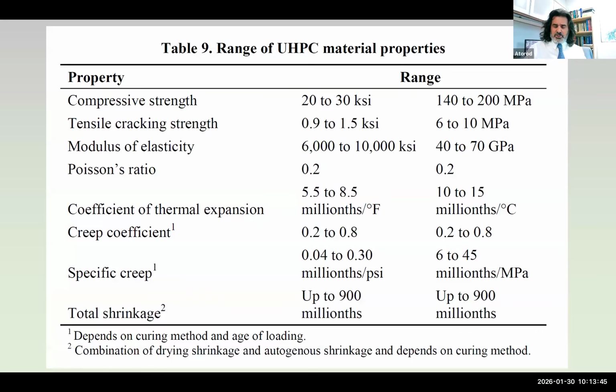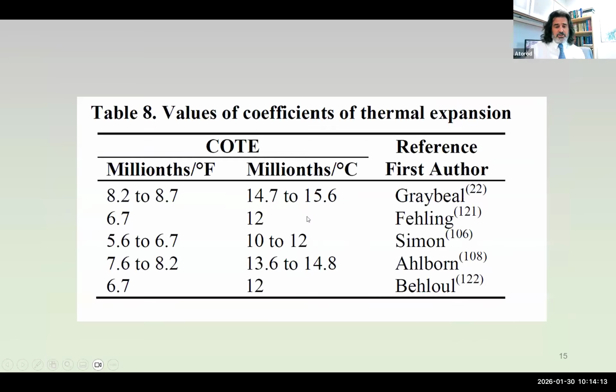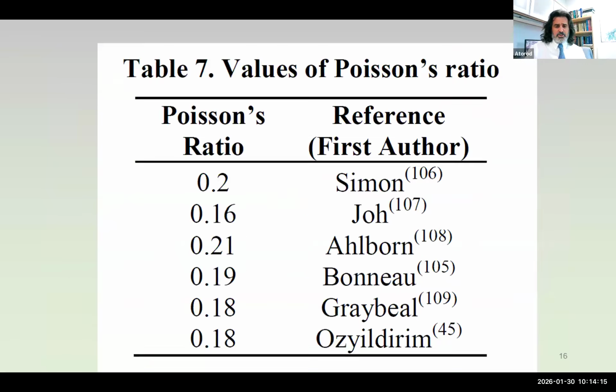Properties, again, I'm going to give you a copy of the slides. I'm not going to go through everything, but look at over here. The tensile capacity is very high. Compressive strength is very high. There is a shrinkage involved with this, a little bit higher than the conventional concrete. Specific creep is a little bit lower, which is good because there's not that much water in it. The thermal expansion coefficient is a little bit high compared to conventional concrete. So I'll give you some properties, you can look at it.